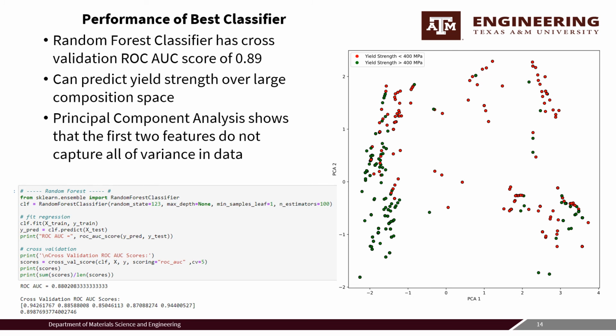The best performing classifier was the random forest, and it had a cross-validation receiver operating characteristic area under the curve score of 0.89. This isn't a perfect score, but the random forest classifier is still able to pretty accurately predict yield strength over a large compositional space. It is also important to note that through principal component analysis, it was shown that the first two features do not capture all of the variance in the dataset.